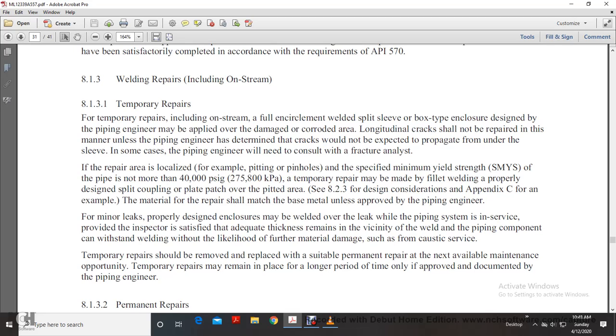In some cases, the piping engineer will need to consult with fracture analysis if the repair area is localized. For example, for pitting or pinhole leaks where the specified minimum yield strength of the pipe is not more than 40,000 psig, the temporary repair may be made by fillet welding and a properly designed split coupling with a plate patch over the affected area, per section 8.2.3 and design considerations in appendix C. The material for the repair should match the base metal unless approved by the piping engineer. For a minor leak, a properly designed enclosure may be welded over the leak while the piping system is in service.